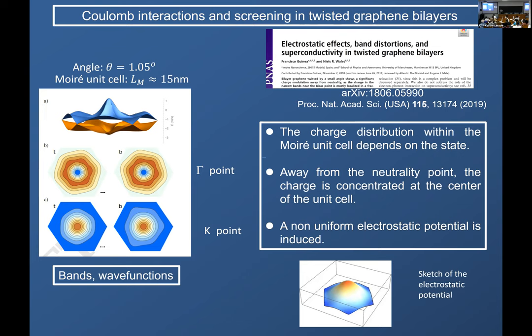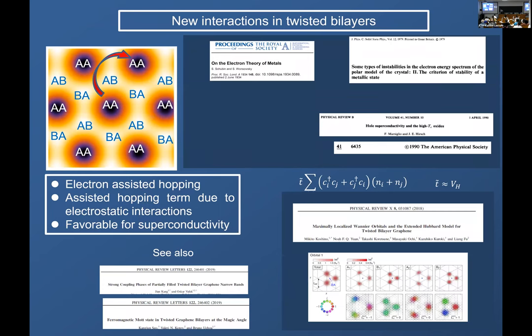So you create this potential, this electrostatic potential. You create it by changing the filling, and it affects states at gamma and at K differently because they have associated charge distributions which change from place to place. Because of that, as I will show you later, you're not only shifting the band, you're changing the shape of the band itself. Because the states at gamma do not feel this potential—they are uniformly distributed in the unit cell and this potential has zero average—while the states at K are strongly pushed up or down by this potential you create when you dope the system.